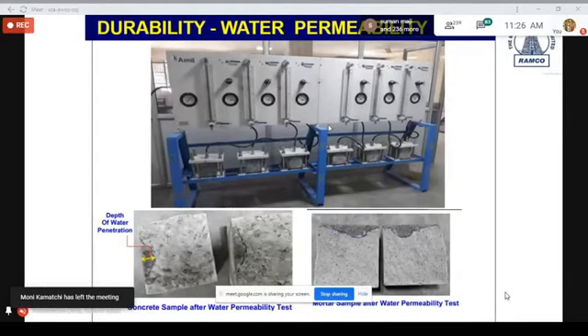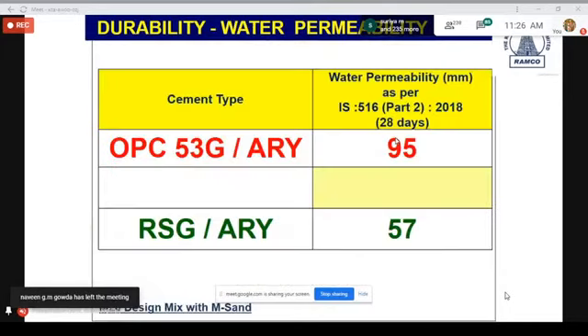So that is what you will find, that the water permeability in mm as per IS 516, after 28 days, this is the difference of water permeability, which you can see, 95 mm or 57 mm. So this is something which is of very much interest. This is for M20 grade of concrete, where M sand has been used. So this is how you will find that water permeability results are there.